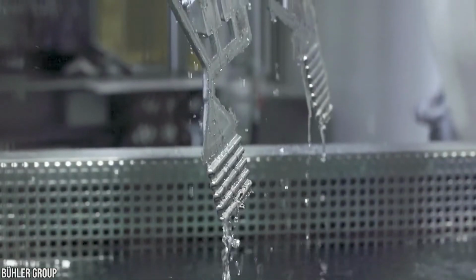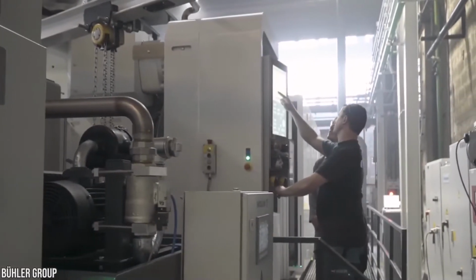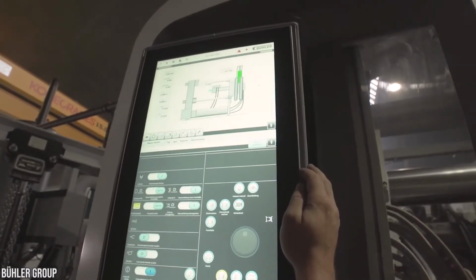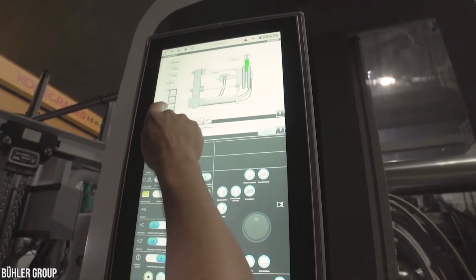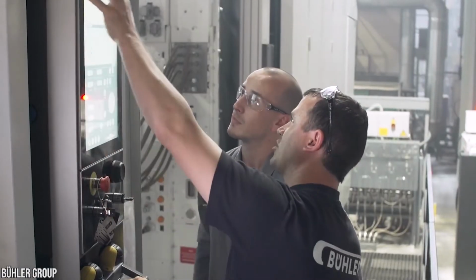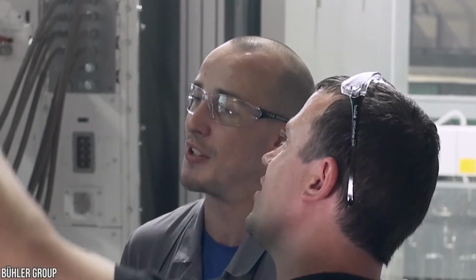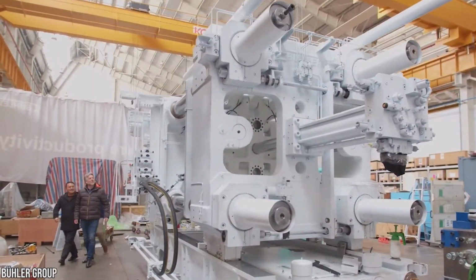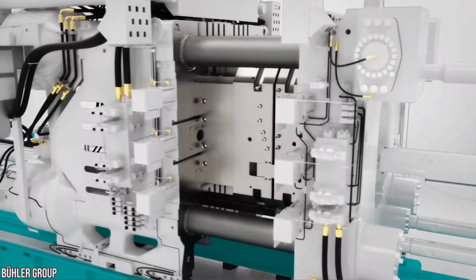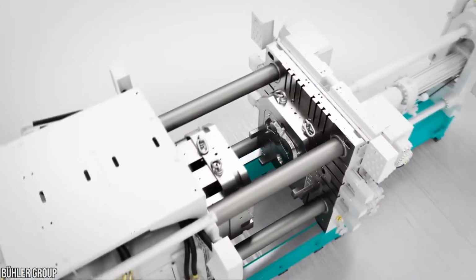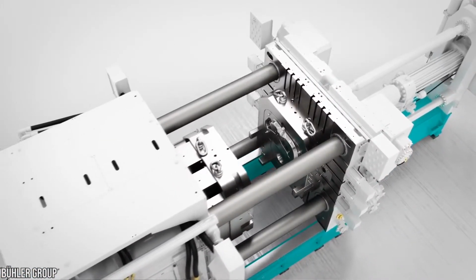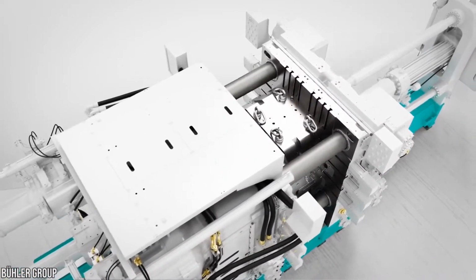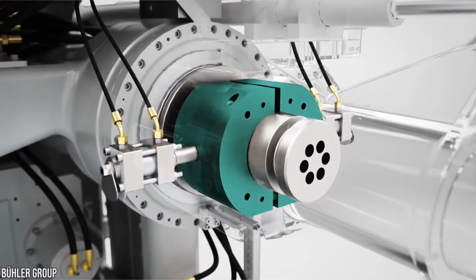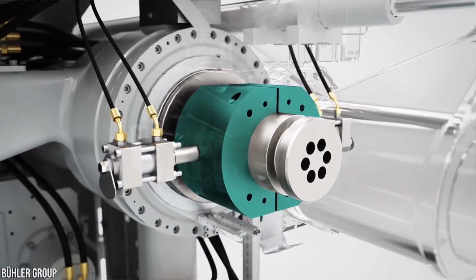Then the casting is ejected from the die at 400 degrees centigrade. The raw casting is then placed in the quenching tank to reduce the temperature from 400 to 50 degrees centigrade rapidly. It helps tackle some defects and increase some material properties. Cool the open die to 150 degrees centigrade, thoroughly clean it with robots, and prepare it for the next cycle. The next casting cycle begins usually 1 to 2 minutes after the current one finishes.